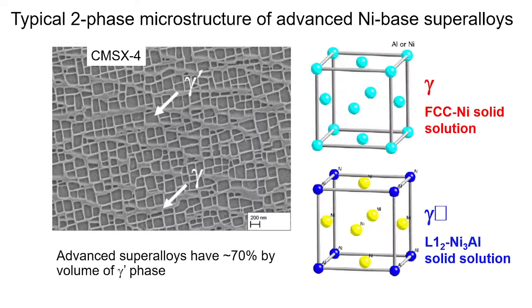And the reason this alloy is so effective at high temperatures is that it's actually a composite structure. It is a two-phase structure. It's got these little cuboidal precipitates of ordered gamma prime, with nickel atoms on the face centers and aluminum atoms on the cube corners, and the thin regions in between are the disordered FCC phase. So it's mostly an FCC gamma solid solution. The volume fraction of the second phase can be as high as 70%. So a very high volume fraction of second phase precipitates.